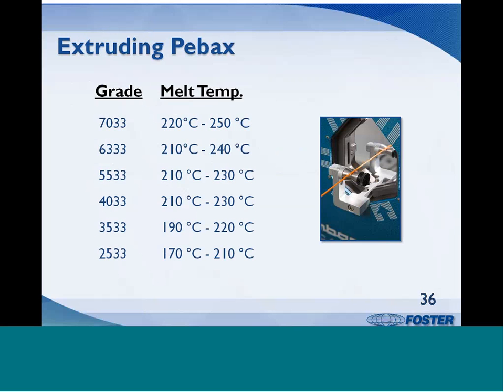This chart shows the melt temperatures recommended for extrusion. As with injection molding, there is a direct relationship between hardness and required extrusion temperatures.